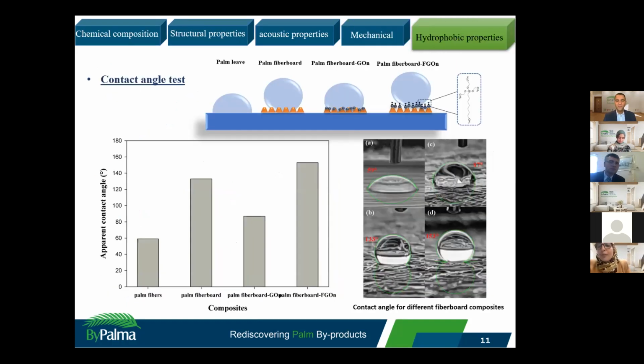So in order to improve the resistance of the prepared fiberboard to water penetration, making them less susceptible to changing their dimensional properties, the swelling of the fiberboard panel can be decreased by enhancing the hydrophobicity of the prepared fiber. So in this work, functionalized graphene with long chain grafted silane molecules was used in order to enhance the hydrophobicity of our work.